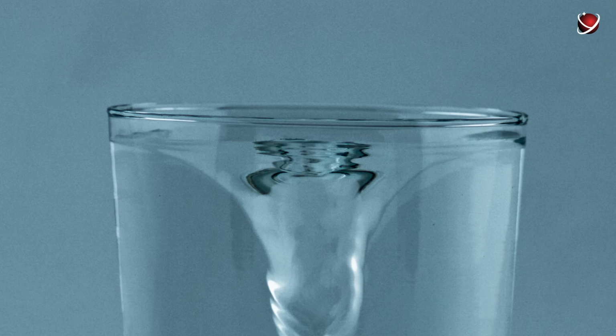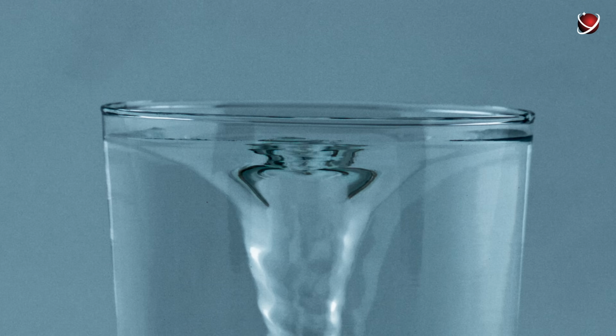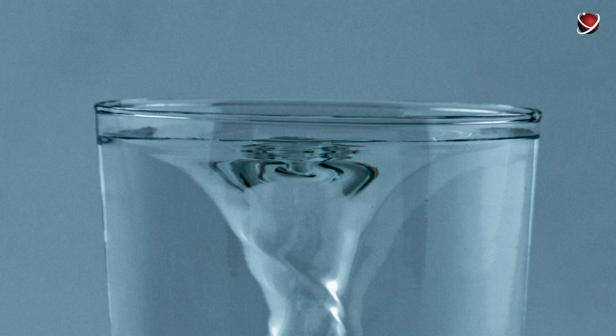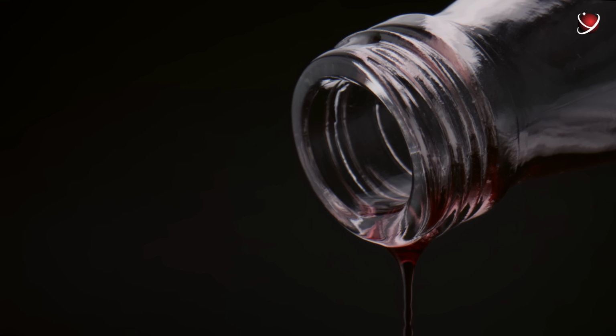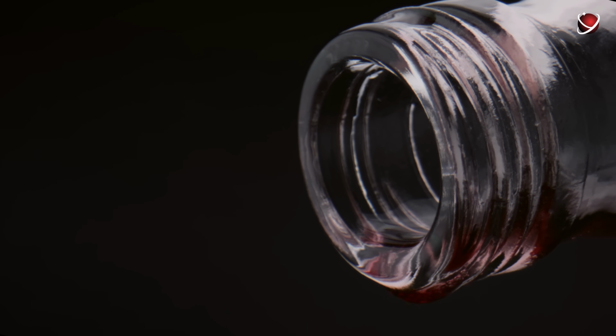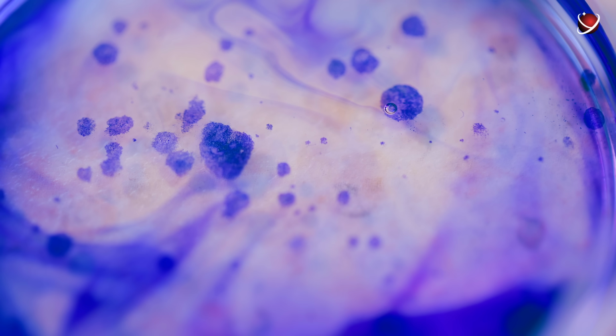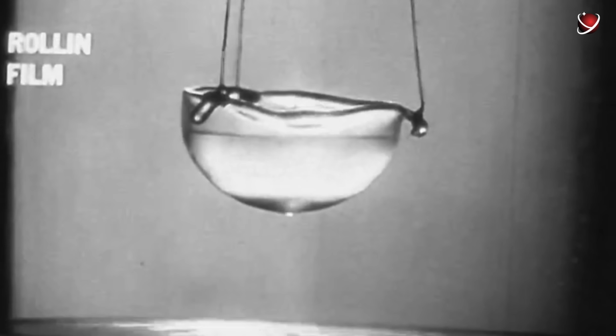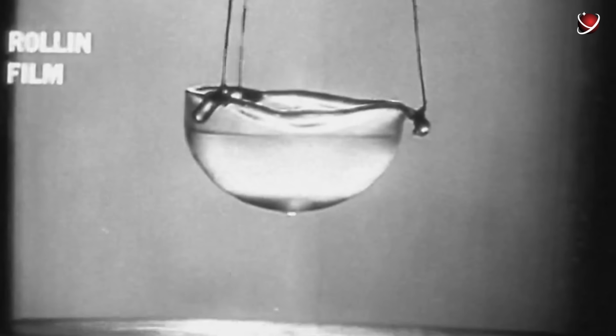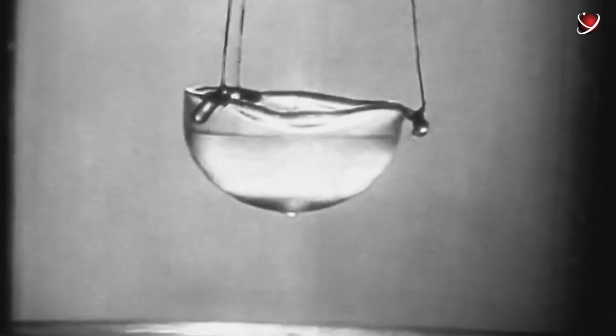Superfluidity is the property of a liquid with zero viscosity. Being superfluid, helium-2 can permeate ceramics with pores as tiny as half a micron in diameter. No other known material can do that. There are two other experiments that vividly demonstrate this effect. If you pour helium-2 into a cup, filling it only halfway, you'll see a thin layer known as the roll-in film crawling out of the cup's sides before dripping down. Alternatively, if you dip a capillary tip tube into a container with helium-2, a fountain of this superfluid will almost instantly eject from the tip.